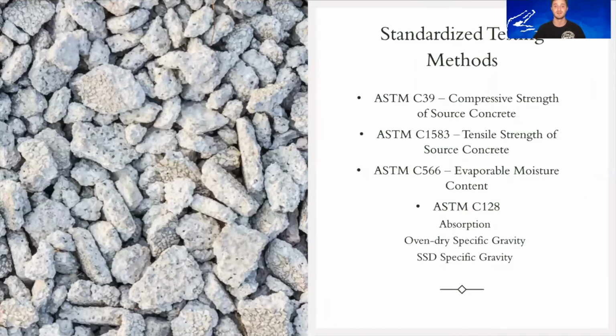Moving on to the standardized testing methods we use for evaluating recycled concrete aggregate. The tests are performed in order to determine the necessary material properties of the RCA, which are performed following ASTM standard test methods. The compressive strength and tensile strength of the source concrete are obtained by following the testing procedures outlined in ASTM C39 and ASTM C1583 respectively.